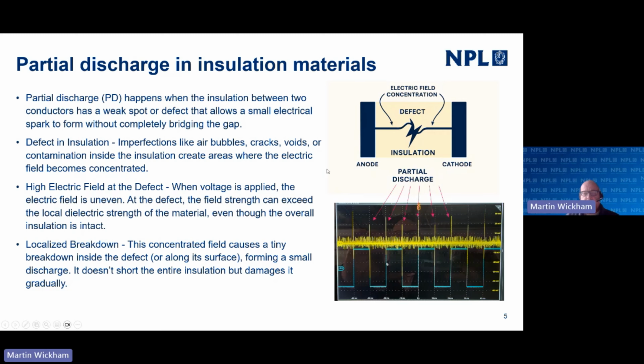These could be cracks, air bubbles, voids, contamination inside. It's usually an area where, as I say, the dielectric performance is less than the surrounding matrix. And where you have that problem, you can see these spikes occurring. These are signals on the ground line, and you can see that there's a discharge occurring, these tall spikes here, across that defect. It's a localized breakdown occurring somewhere inside this insulation, and it's a relatively small discharge. So, okay, potentially annoying, potentially noisy.